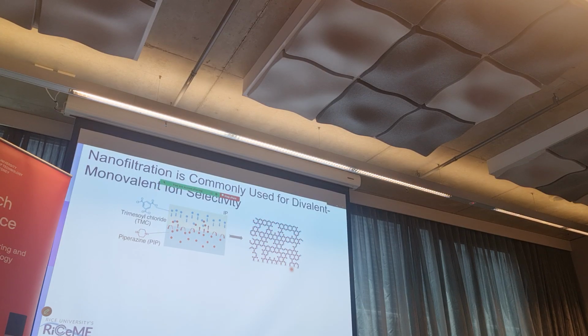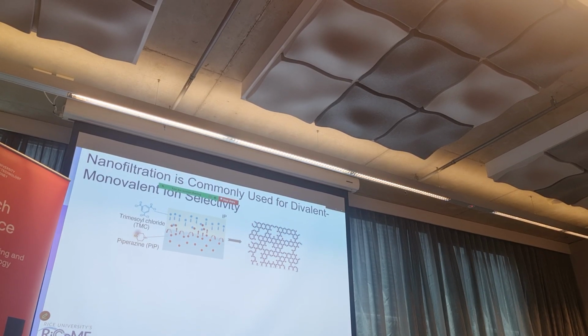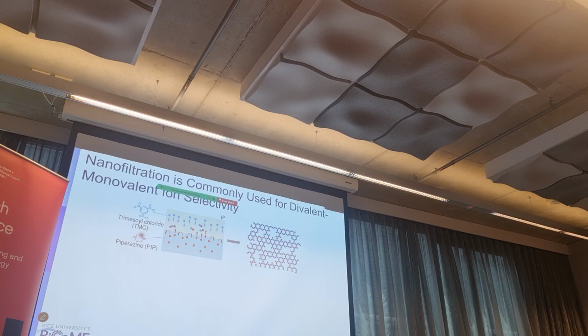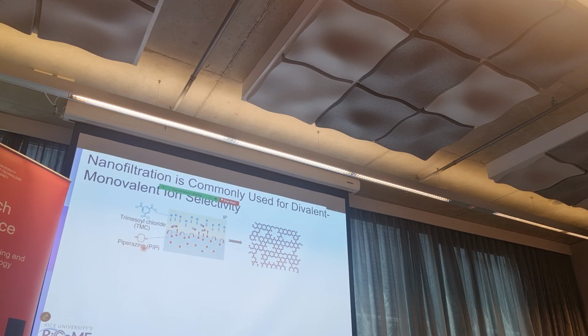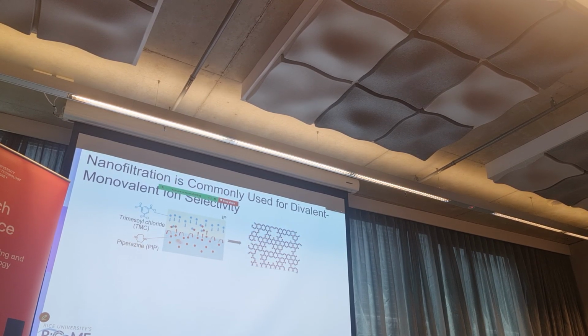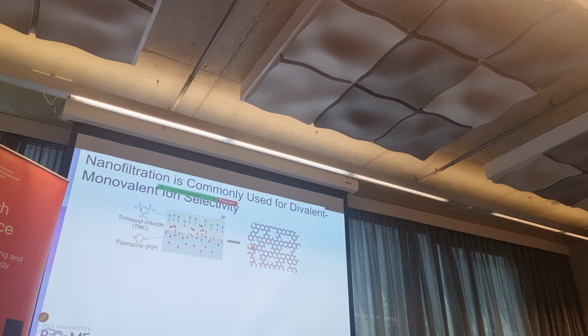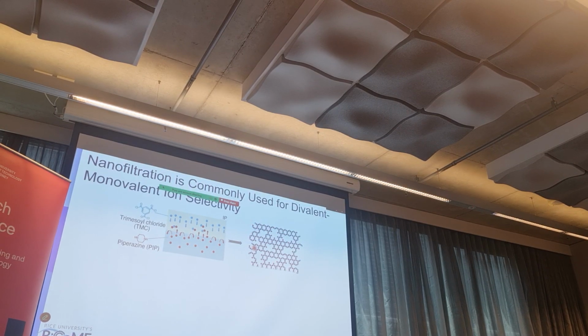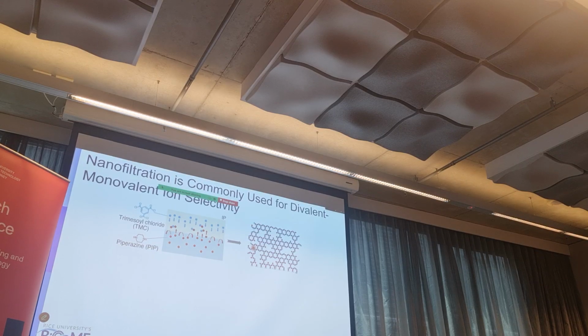The way we make a nanofiltration membrane, we have interfacial polymerization between trimesoyl chloride and piperazine, and it's a very uncontrolled reaction. So we can get a thin film that does the separation, but because it's an uncontrolled reaction, we have a pore size distribution - it's not a uniform pore size.